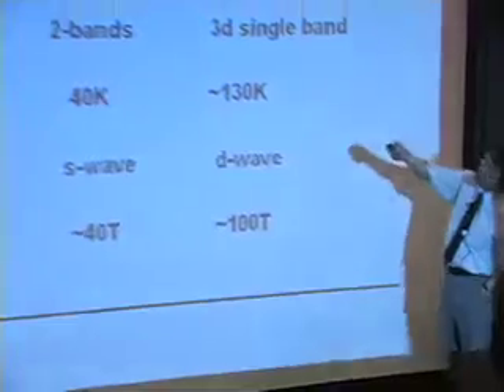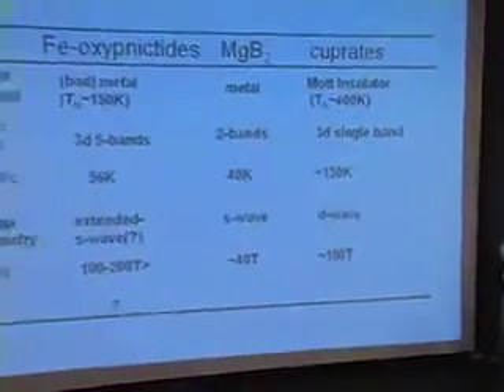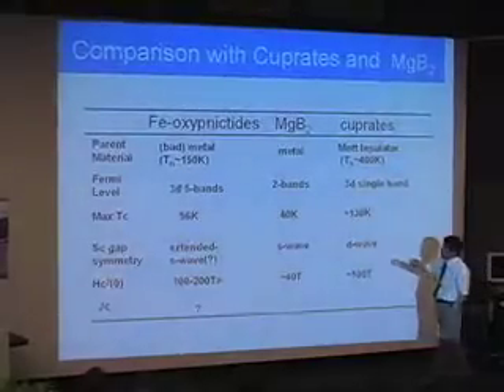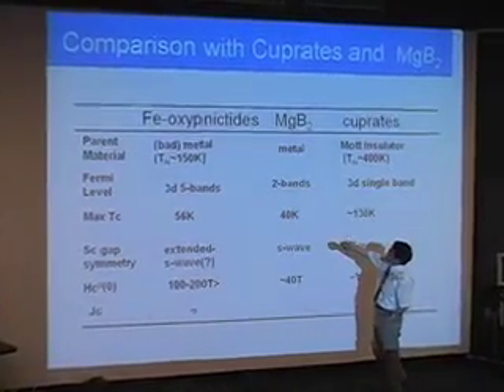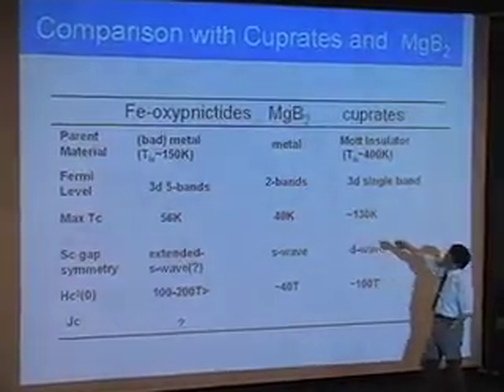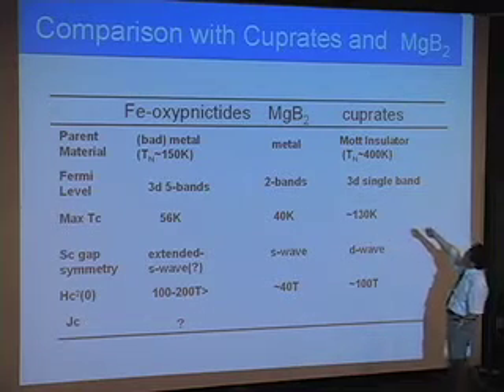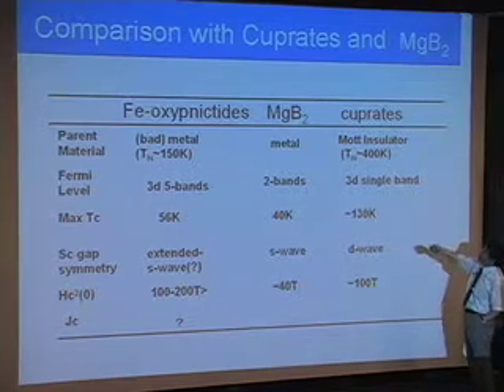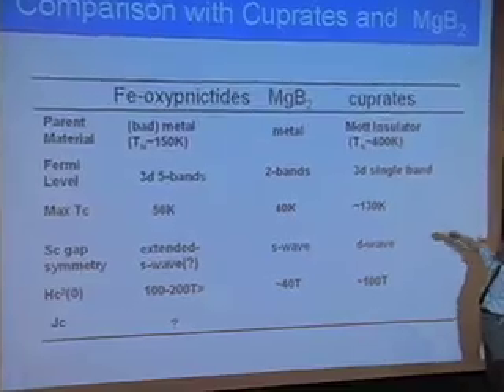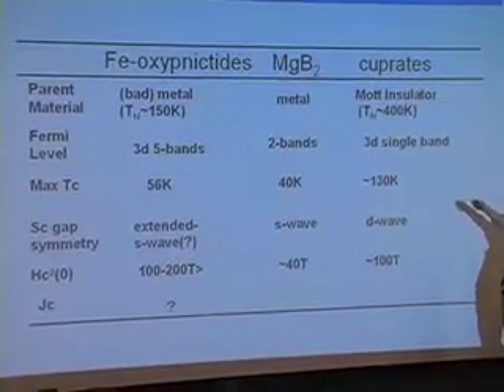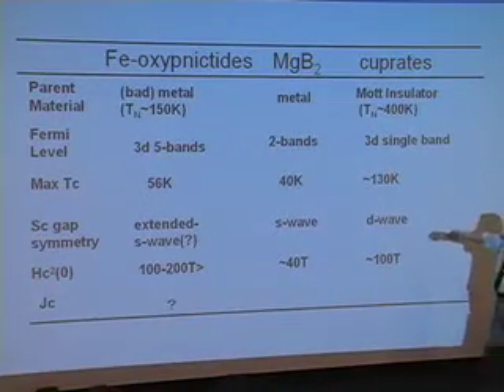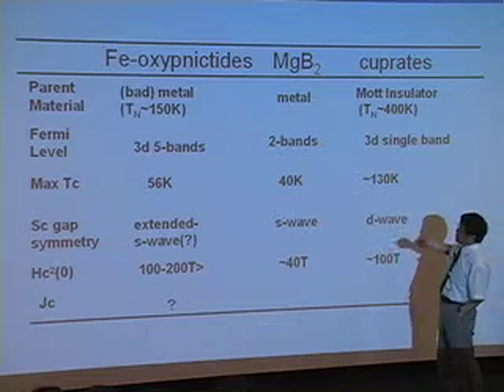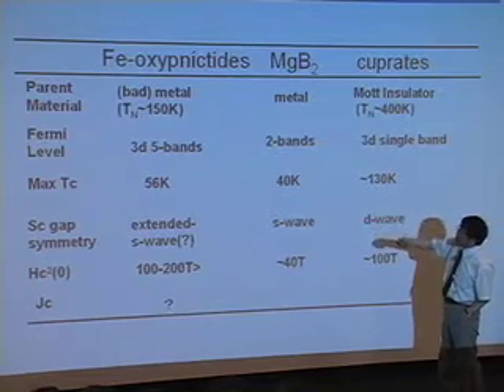This is a property comparison among three typical superconductors: iron-based superconductors, metallic superconductors, and cuprates. The highest Tc is the cuprate, which is the best in terms of maximum Tc. But the iron-based superconductor is quite interesting.